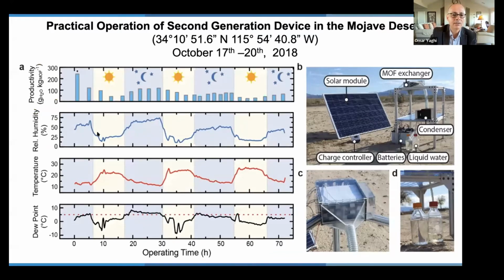And you can see here in the Mojave Desert, the relative humidity during the day and night. And during the day, it goes down to about 7% relative humidity, and the MOF is still taking up water. Okay, so this basically realizes my dream of harvesting water anywhere at any time of the year, because this MOF is capable of taking up water at very low humidity.